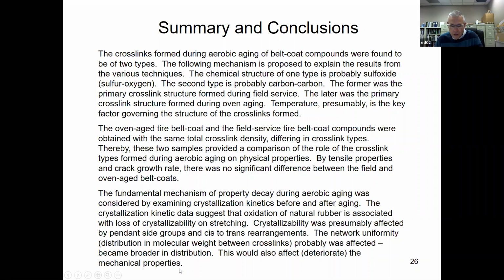In other words, if you're looking at a non-crystallizing rubber, such as SBR, when it's oxidized, it's also associated with increase in modulus, loss of elongation to break, and also a loss in tensile strength. So we would say probably the reason in that case, it's non-crystallizing rubber, is that the network uniformity has been affected. Okay.